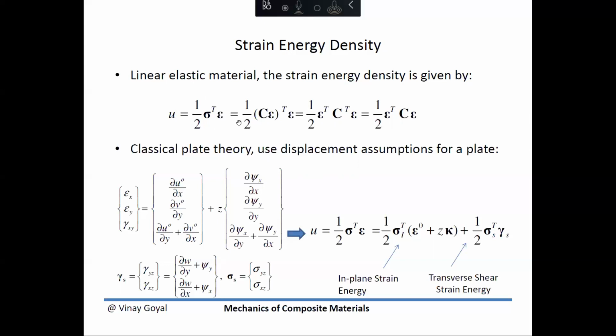If you recall, the strain energy density was defined as a stress transpose times strain. Stress equals the C matrix, the stiffness matrix, times the strain. We can now distribute the transpose over here in this manner, and that means I have to reorder this in this manner. C is a symmetric 6x6 stiffness matrix, which then basically becomes this. We're going to now apply the assumptions for first order shear deformation theory. So this is the strains, and this is your strains, the transverse shear strains. And what I'm going to do, I'm going to put everything in a vector so it's easy for us to track what is going on.